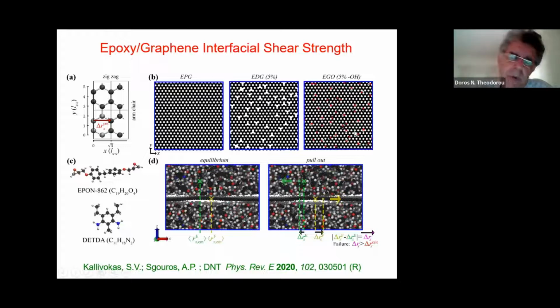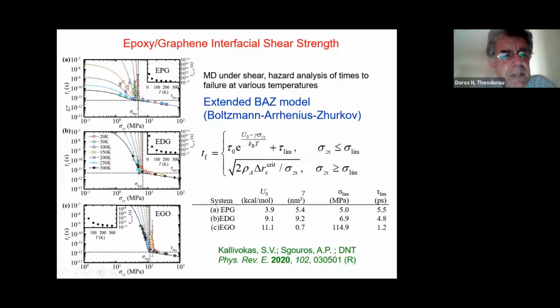And to define what we call the failure of the interface, we said that whenever the displacement of the graphene in relation to the polymer exceeds the surface unit cell parameter of the graphene, this delta Rx that we show here, then a failure of the interface has occurred. So we performed many molecular dynamics simulations under different forces imposed on the system and under different temperatures, and measured the time to failure as a function of these stresses and temperatures. And the results look something like that here.